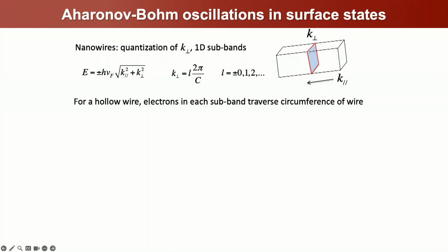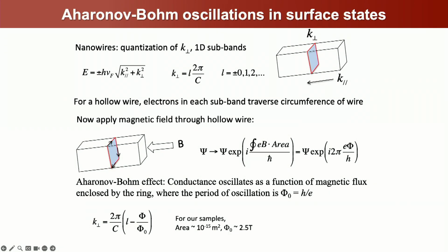So to see Aharonov-Bohm oscillations, we want to start with a nanowire that's narrow enough that you can see 1D subbands, and so your conductance should be quantized into these 1D subbands. And if you have a hollow wire, then the electrons should traverse the circumference of the wire. There shouldn't be a bulk. If the bulk is insulating and the surface state is dominating, then the electron should go around the surface state. Now, if you apply a magnetic field through a hollow wire, you accumulate a phase. That's just your Aharonov-Bohm phase. And this phase will cause the conductance to oscillate as a function of h over e.